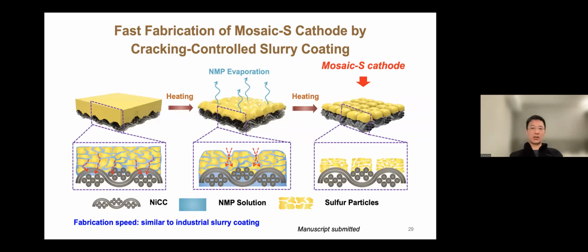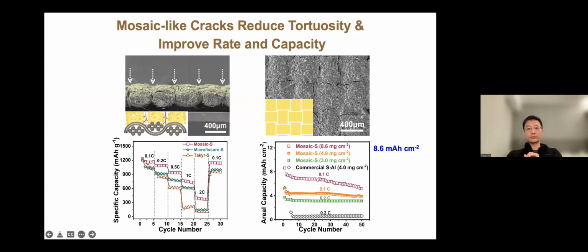So we think, can we again engineer something so that we'll be able to coat the sulfur as we coat a normal slurry on top of the current collector and still achieve a very high capacity, right? So we did that, and what we found is that we simply need to control the evaporation rate and the viscosity, so that we can control the formation of a mosaic-like sulfur, just like the mosaic structure we have in the kitchen or in the toilet. And this can be done very easily on our metallic textiles, because during the wet drying process, this liquid film will be pinned on the protrusions of each woven structure, and the pinned area will form a thicker sulfur. The unpinned area will form more deep cracks, right, and generate this kind of structure. And it looks like this, right?